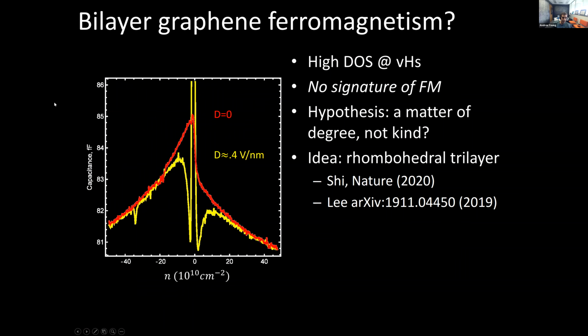In fact, this is a measurement of the capacitance of two gates, and I'll get back to this a bit later, where you're measuring the electric field that penetrates through a bilayer graphene layer at 0 applied electric displacement field and at large applied electric displacement field. And what you see is basically well captured by the single particle picture.